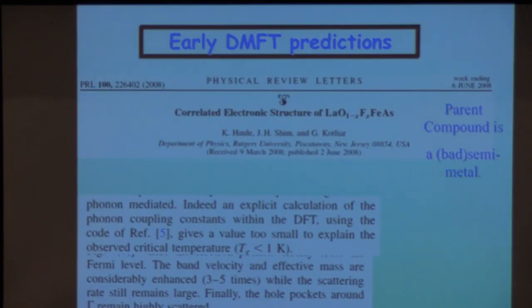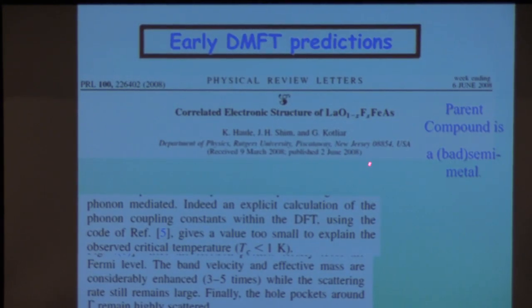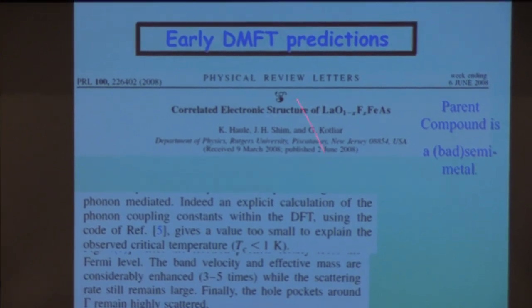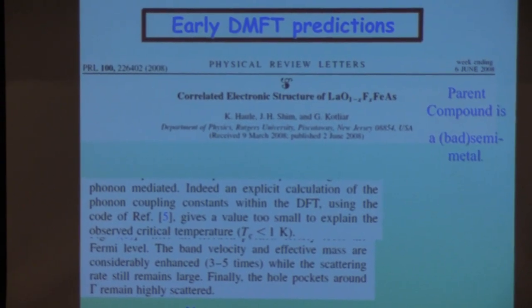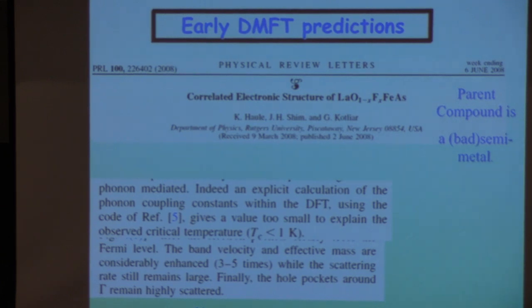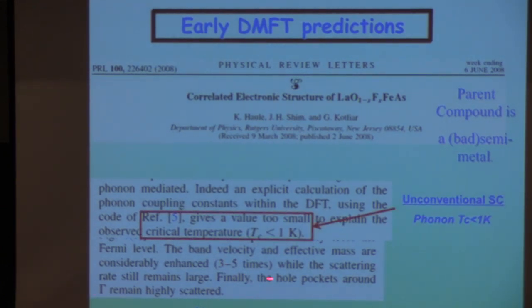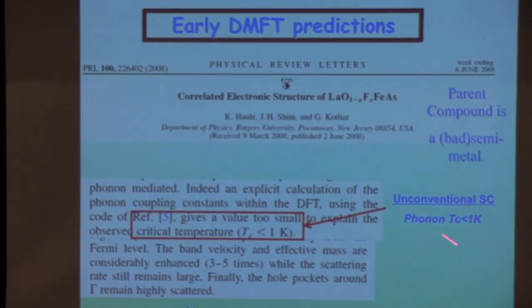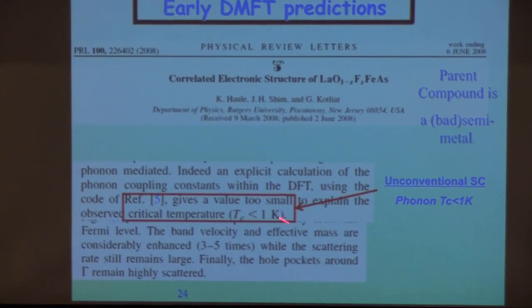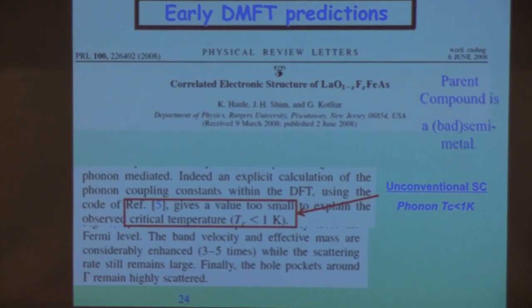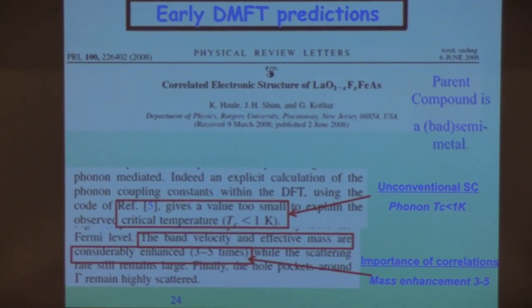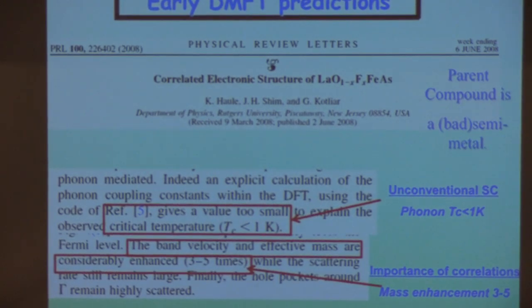Okay, so what did we do? As soon as the experiments came, within a couple of weeks of the experiment, we were able to actually run our calculations and see what they had. And we said a few things. First of all, we computed electron-phonon coupling and argued that the Tc due to phonons was negligible, so this was an unconventional superconductor. And the other thing is we estimated those mass enhancements, and we said that the masses relative to the band theory were enhanced by a factor of 3 to 5. So we pointed out already at the very beginning that the material was very correlated.